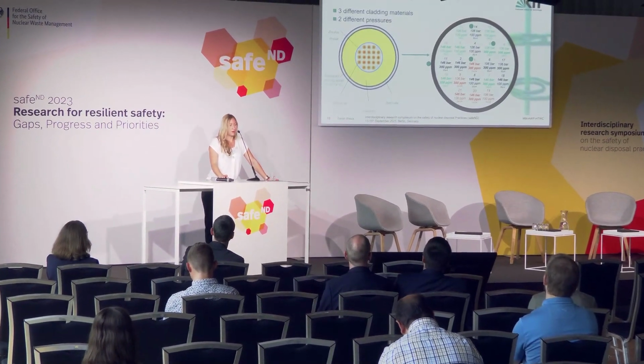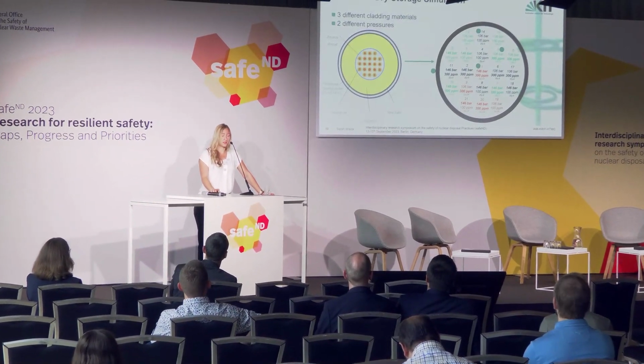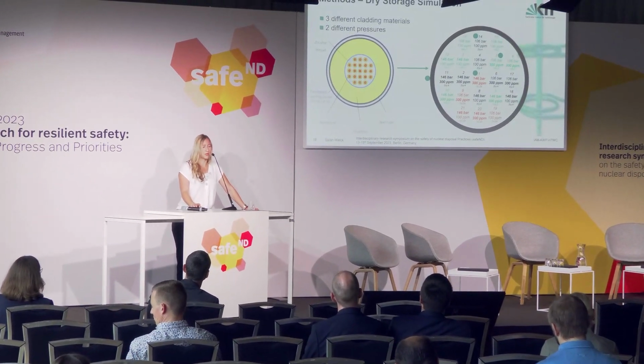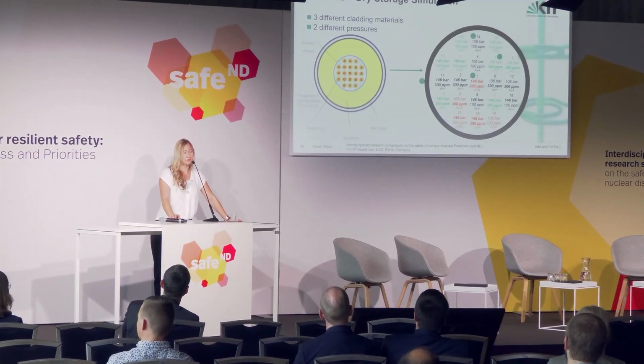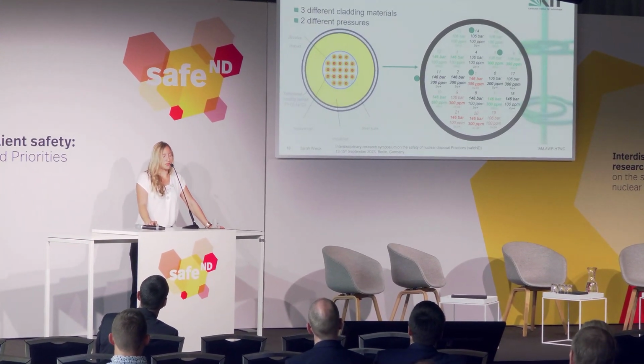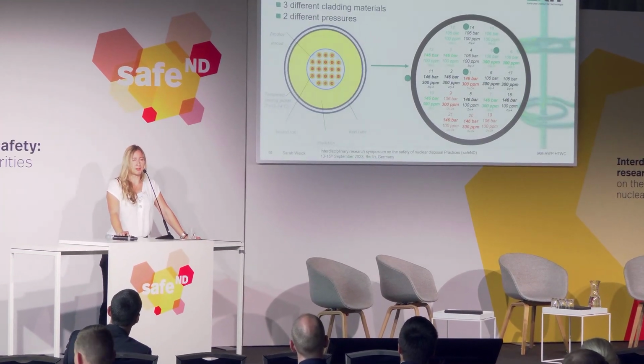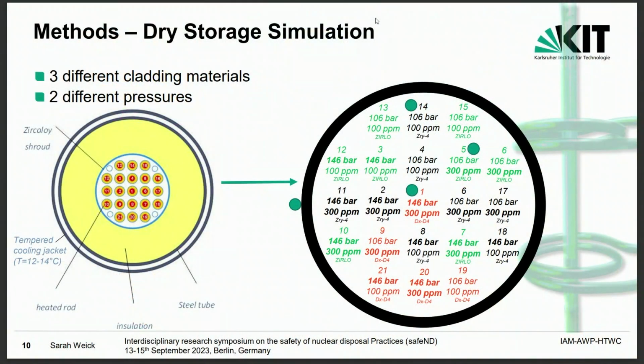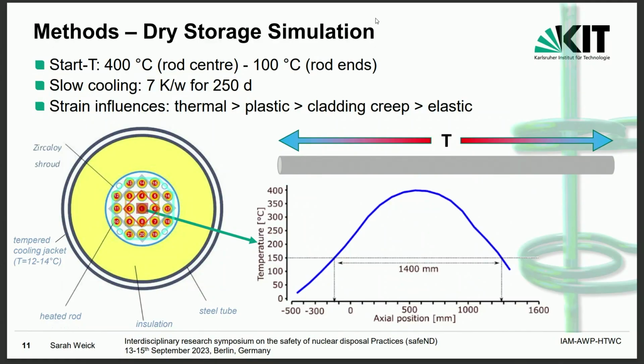This is then the kind of schematic illustration of how the bundle looks like with the different conditions of all the materials, all the pressures, and the hydrogen concentrations. You'll see that we have those 21 different cladding tube conditions, but then again, through the whole rod, we have as well a temperature decrease through the ends. So we have different temperatures in one rod as well, which means that we will have several different results when the experiment is at the end.